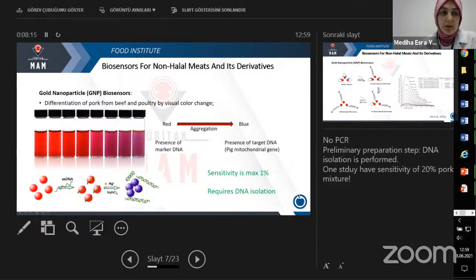This is a very basic biosensor though. So normally you have the gold nanoparticles with the marker added inside. You just put your sample in, add the salt solution, and wait for the color change. The sensitivity of those types of biosensors is maximum 1%, but there are some studies with sensitivity around 20% porcine mixture. So it's not very sensitive though, but if you're a consumer who buys some meat from the butcher and wants to check it, it's a good and basic way of a biosensor. The problem with this biosensor is that it requires DNA isolation as the preliminary preparation step.